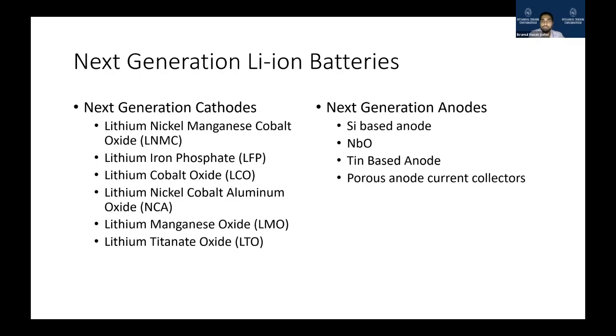If it is using a graphite anode, and you are fast charging it because you have a high voltage fast charging system, it will plate lithium on the surface of this graphite. That will make your battery vulnerable to catching fire, because dendrite formation is happening, and then anode and cathode can be short circuited. And that's why if you just have a traditional lithium ion battery, you cannot just fast charge it because you have a fast charger. The battery should be compatible, with an anode which is fast charging as well. So you should understand that it is the next generation anode that is making the lithium battery charge faster, allowing the fast charging.